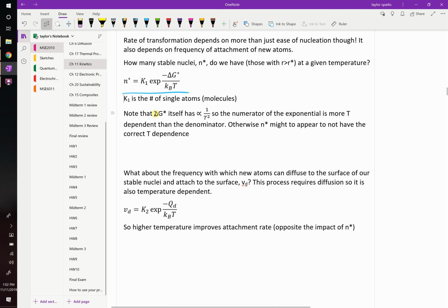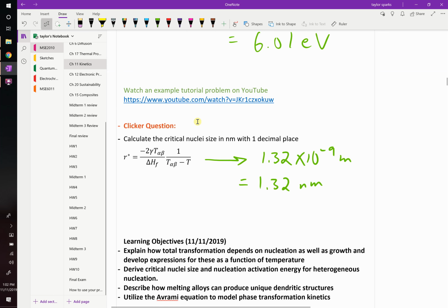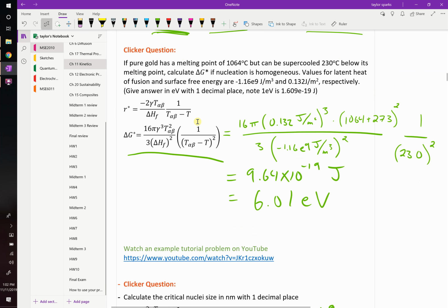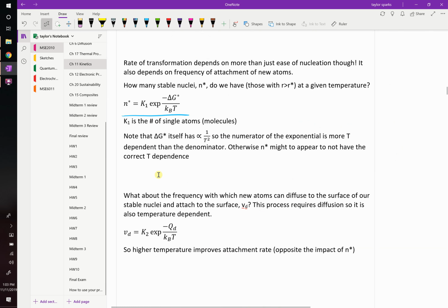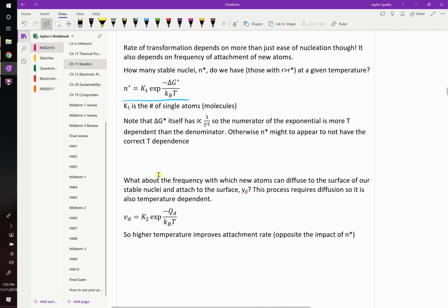Quick thing to note here is that delta G star, if we go back to it up here, right here, is itself a function of temperature. So you have something that is a function of temperature inside of an exponential with temperature in it. Delta G star is proportional to 1 over the temperature squared, right? So when you put that into this expression, you get the opposite dependence that you normally see.